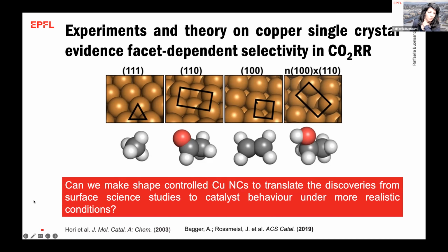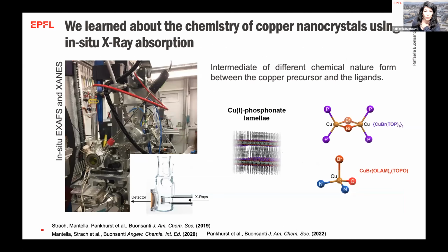100. So the first question to ask is if we could make shape-controlled copper nanocrystals so that we could look into these properties, but under more realistic conditions compared to the experiments that are done in single crystals. So actually what we did to develop the synthesis of copper was to really understand the chemistry behind the formation of copper nanoparticles. So this is a typical three-neck flask that we use for the synthesis of nanocrystals. We brought it to the synchrotron to perform in situ X-ray absorption.